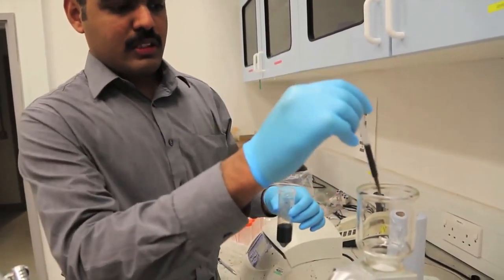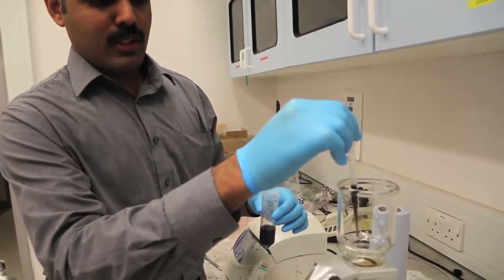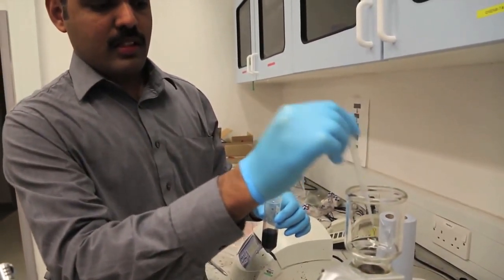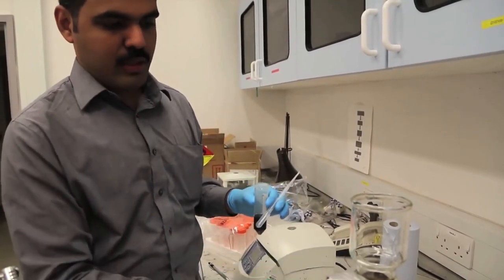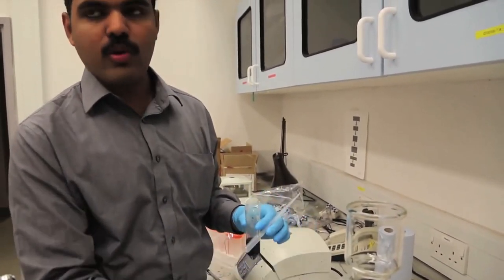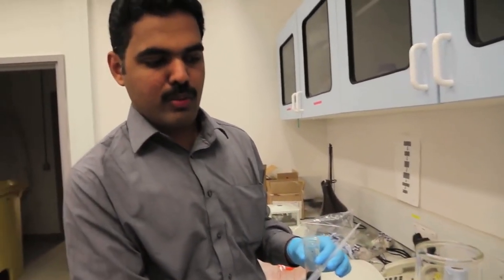Then you use this water on top of this porous alumina membrane. Then you start pumping using a vacuum pump. Then you remove all liquid water through this alumina membrane, and your graphene oxide sheet gets deposited on top of this alumina. And finally, after drying, you can peel off this freestanding graphene oxide, and you can study membrane property, or you can also characterize this membrane using different techniques.